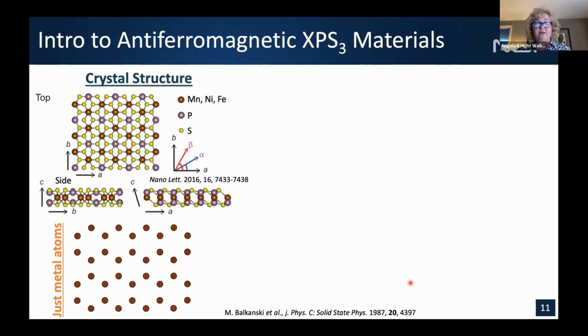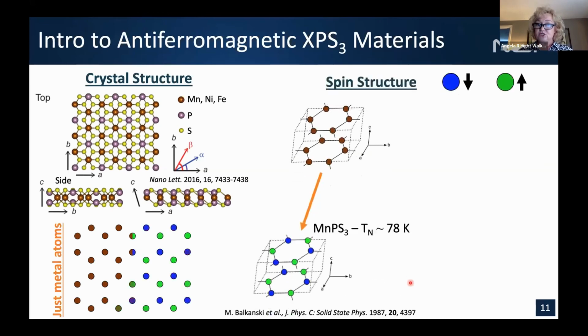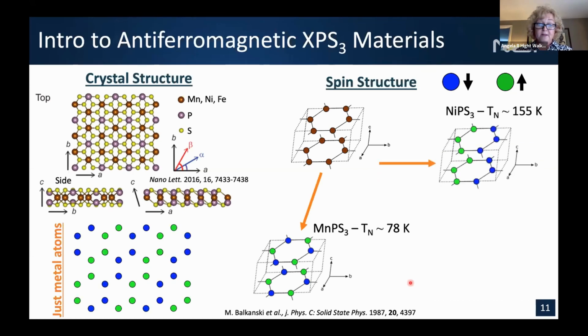So one of the interesting things with all of this family, whether it's manganese, nickel, or iron PS3, is that they have the same crystal structure. And that really, when you look at the magnetic ion, is the hexagon structure from graphene. So we feel very comfortable with that. But what's interesting is that the spin structures are quite different. And of course, their Néel temperatures are different, even changing a factor of 2 between manganese and nickel in this case. But what we can see is that the spin structures are quite different, even between the manganese and the nickel, as we're seeing here.